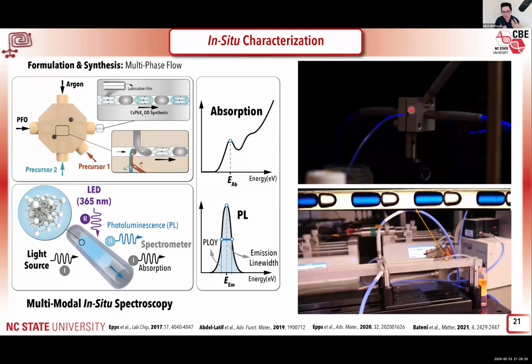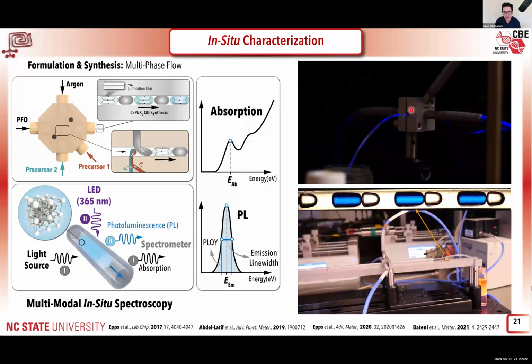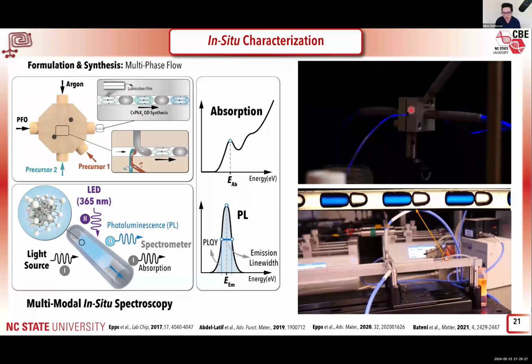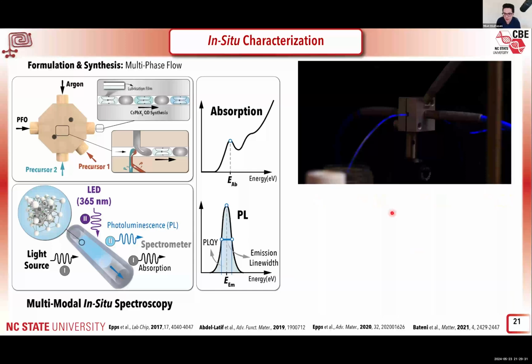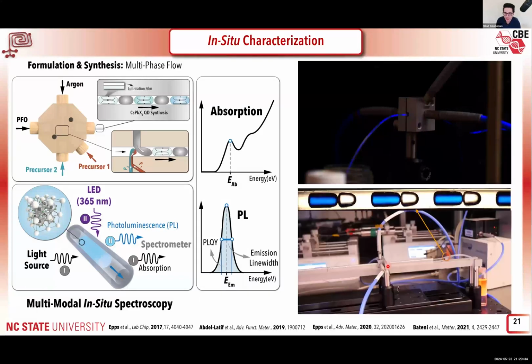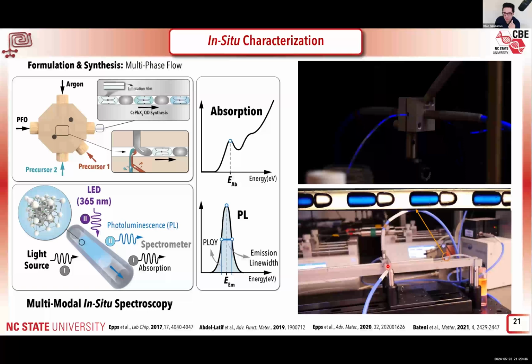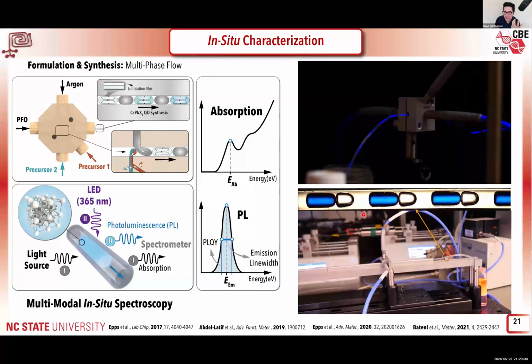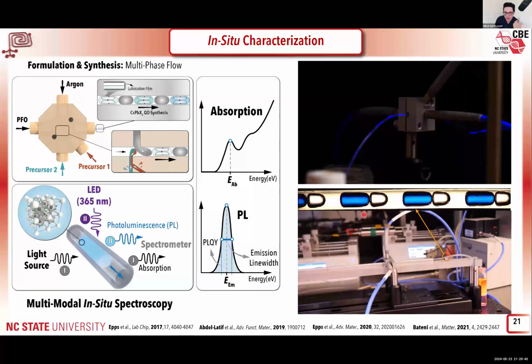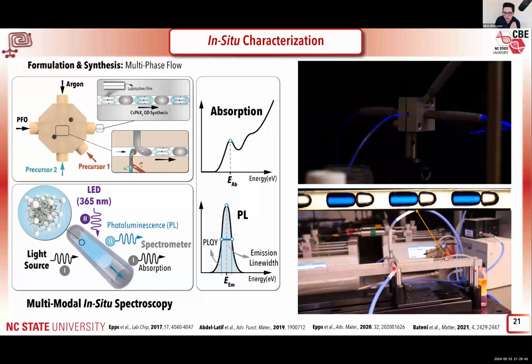Now, if the reaction is fast, in the order of seconds, for example, when you're working on perovskite, metal halide perovskite quantum dots, you don't want to change the speed of the droplets because that changes mixing, and that's going to change the reaction environment within these droplets. We maintain this speed, or we are running these reactions at a constant velocity. We just have this mobile flow cell that moves along the reactor and can automatically detect different positions and do in situ spectroscopy at different positions corresponding to different reaction times.